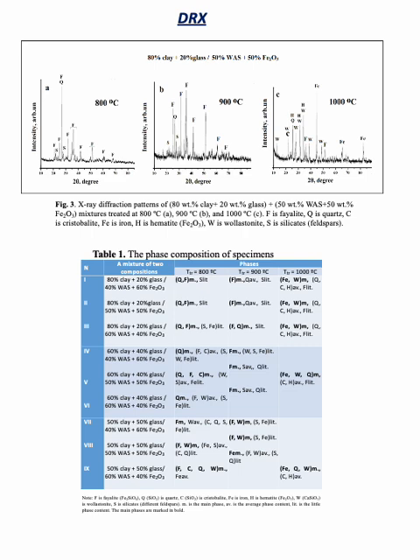X-ray diffraction results show that the temperature treatment of mixtures in the range of 800 degrees Celsius up to 1000 degrees Celsius is accompanied by the formation of a number of new crystalline phases. In the specimens treated at 800 degrees Celsius, the most representative phases are fayalite and quartz, with less representative phases like silicates. It is the same case in the specimens of 900 degrees Celsius. We can observe phases like fayalite and quartz and a small amount of silicate phases. In the mixtures sintered at 1000 degrees Celsius, the phase composition of the samples changes significantly. The main phases are wollastonite and iron, and also hematite.